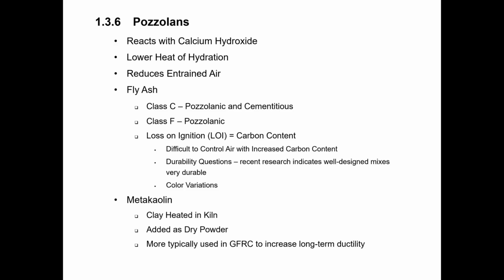Metakaolin is another pozzolan that we see used sometimes in precast, not nearly as commonly as fly ash. Metakaolin is a clay-based material. Just like with the fly ash, it's added as a dry powder. If you see metakaolin used, it's probably more commonly used in GFRC production.